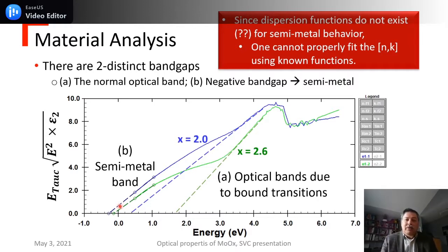Just like if you plotted this up for graphite, which is a very famous semimetal, you would find a negative band gap energy. Well, this is a problem for doing optical analysis because while we have functions to describe bound transitions called Tauc-Lorentz functions, and functions to describe free carriers of metals called Drude-Lorentz functions, we do not have functions to describe semimetals. So it's highly likely that some of the problems that Joerg discovered a number of years ago relate to the fact that this metal oxide is very difficult to analyze because it has semimetal behavior.